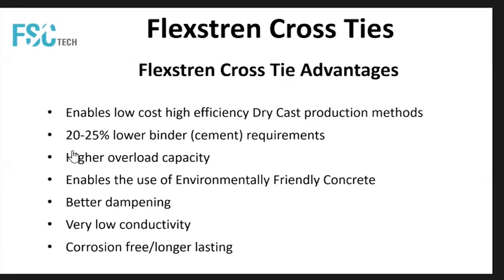If we are thinking of pre-stressing concrete ties, normally you pull the wires at about 85% of yield. This is a composite. Even if you are using basalt, which has a behavior relatively similar to carbon, the maximum you can go is 50%, because it's brittle. So if for a few cycles you get stress levels that are even 2 times that, nothing happens. If that happened on steel, we all know that steel gets relaxed and soon it will fail.